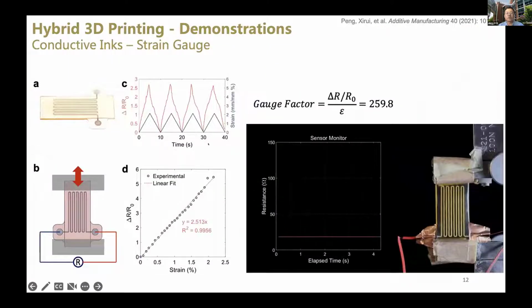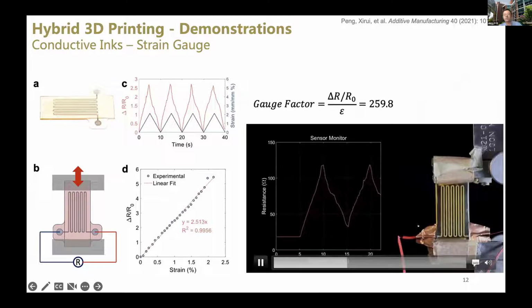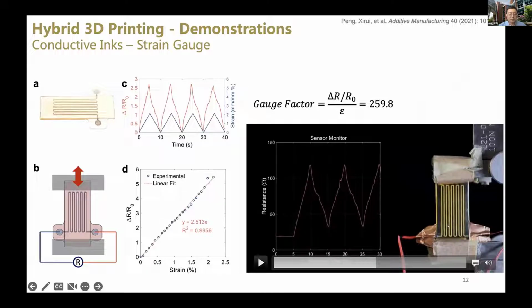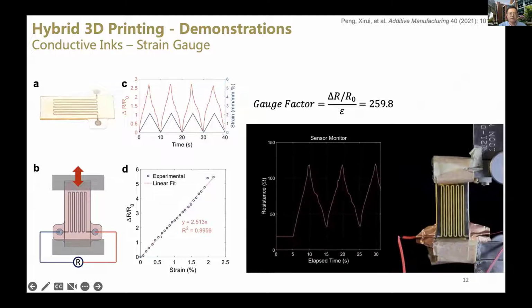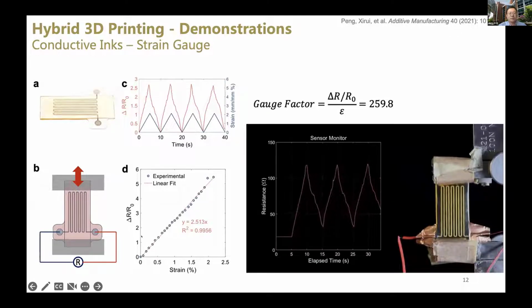And we can also print a strain gauge. In this case, we can use a relatively soft matrix. Then we leave the grooves here. Then we're using DIW to print the silver particle inks. We can print a strain gauge. And so after printing, you can do the testing. This actually shows the resistance change during your cyclic loading of the strain gauge. You can see here, the signal is actually pretty linear with the strain change.